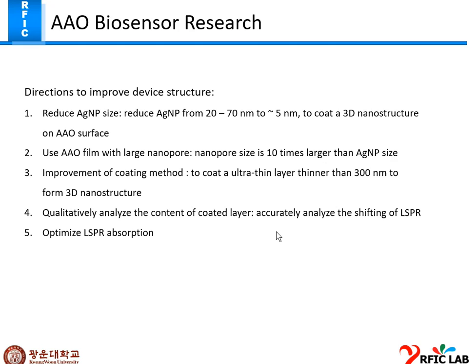The AAO biosensor research is very critical for this, and it's a basic direction to improve the device structure. So we reduce the Ag nanoparticle size from 20 to 70 nanometer down to 5 nanometer to coat a 3D nanostructure on the AAO surface, and also use AAO film with a large nanopore size, 10 times larger than the Ag nanoparticle size. There is also an improvement of the coating method, because we have tried several coating methods like spin coating, dip coating, and drop casting.